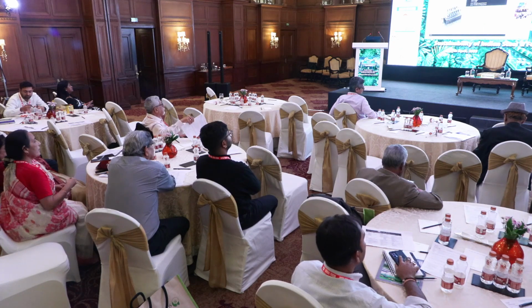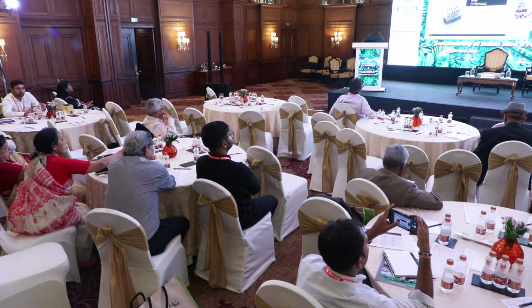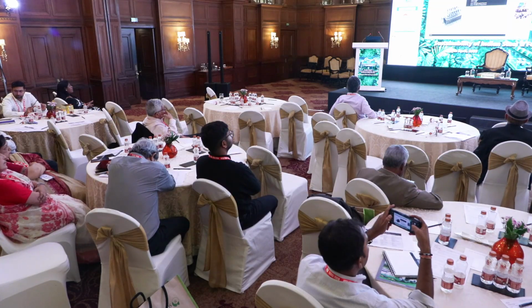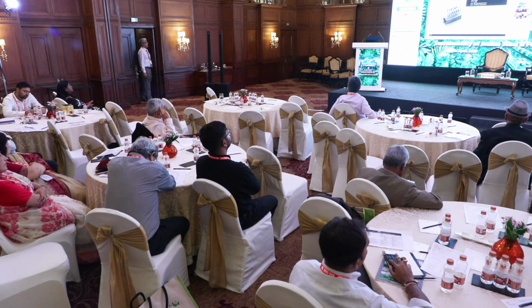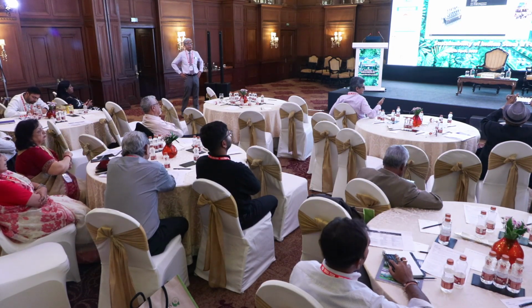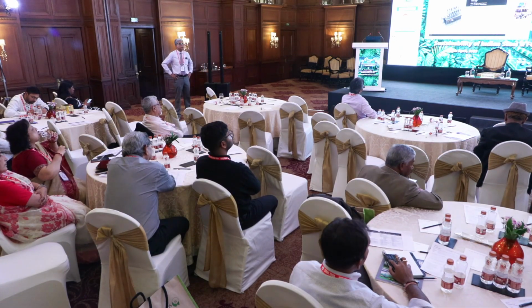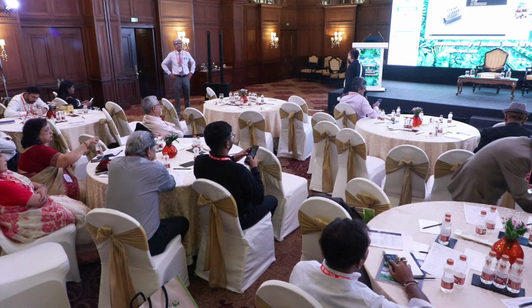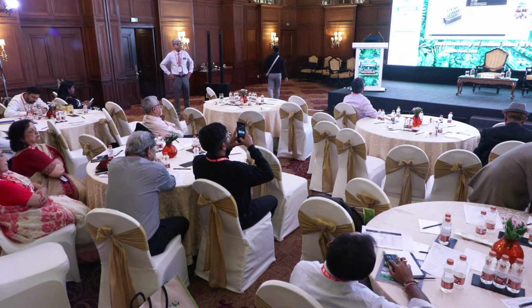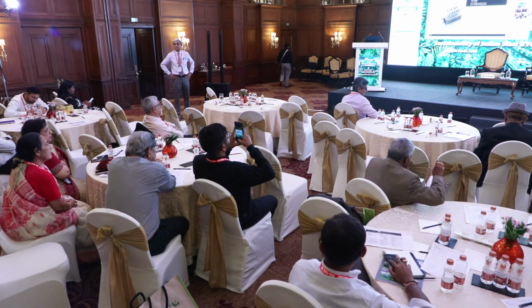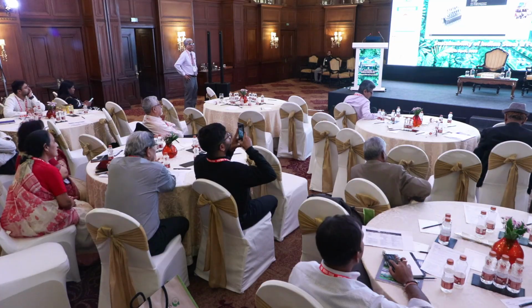Gas cleaning, digital systems, and the capacity, like I said, why we need such big capacity is because the blast furnaces, they are huge. When the steel plants are replacing the blast furnaces, they can get this 2 million, 2.5 million tons DRI capacity if you put a big matrix there. Then you need 2 big furnaces for smelters to create the molten metal. And the difference with the arc furnace is that we are removing the slag, we are removing the gangue here without iron losses. We have a closed furnace, no air ingress here. We have a highly reducing atmosphere here. So we are making the final reduction, removing the slag without excess iron oxide losses to the slag. So no iron losses here.